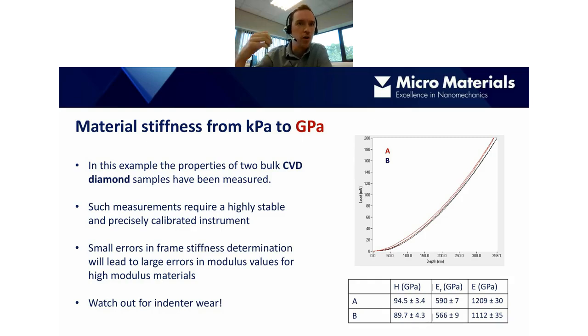But we can also test very, very high stiffness materials. This is an example, again, from one of our NanoTest systems, of indentations on two synthetic diamond coatings. We can see the hardness down here around 90 gigapascals, the reduced modulus around 600, and that equates to an elastic modulus of over 1,000 gigapascals. In order to accurately measure materials of this hardness and high stiffness, it's important that we have a stable and precisely calibrated instrument. As I mentioned briefly in the section on frame stiffness, any slight error or inaccuracy in the frame stiffness determination will give us large errors in the modulus values.